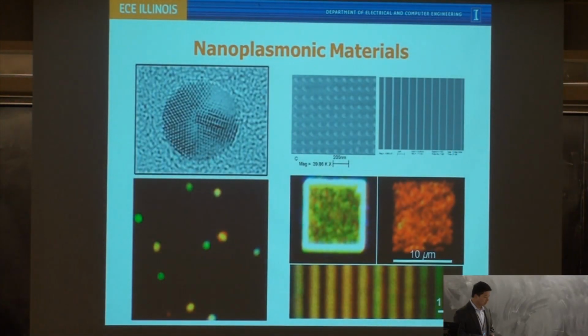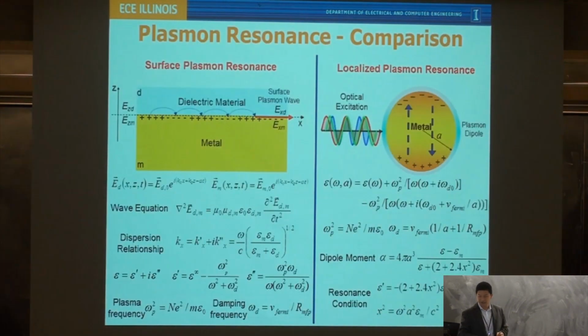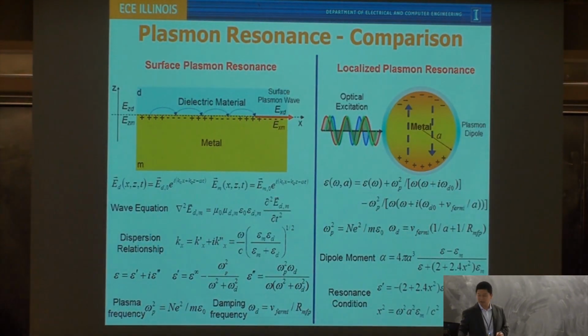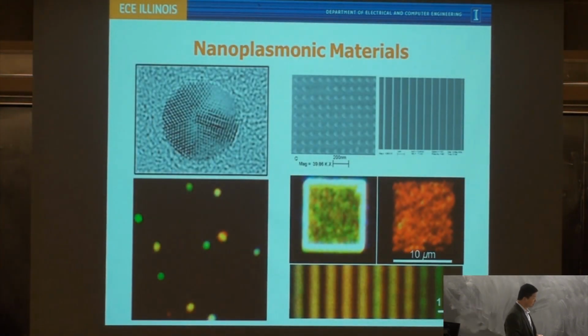All right, let me move to the actual engineering side of it. So this is what we make in our lab. Of course, you can always do the simplest way. You can purchase a lot of nanoparticles from so many companies nowadays that make nanoparticles out of silver, gold, or even copper. If you do a dark field scattering imaging of those particles, you will see each of them exhibit a very distinctive scattering color, because they have this plasmon resonance mode in their cavity. Depending on the actual material and dimension and size of the particle, you're going to have different color emitted from the particle. Of course, that's what chemists do mostly.